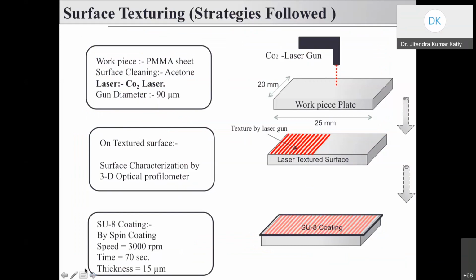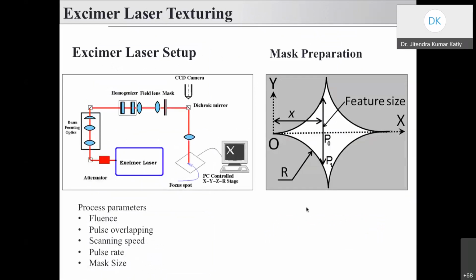Now I will show you one example of surface texturing and how it improves the life of the surface. Here we have the workpiece, and we have the CO2 laser gun, and we perform the texture over the surface, using a gun diameter of 90 micron. We can perform surface characterization by 3D optical profilometer, and then we can coat SU8 polymer over the substrate and perform the tribological test. For texturing, we use a mask. That is very important. Other parameters very important to control are fluence, pulse, scanning speed, pulse rate, and size of the mask to get proper textures over the surface.